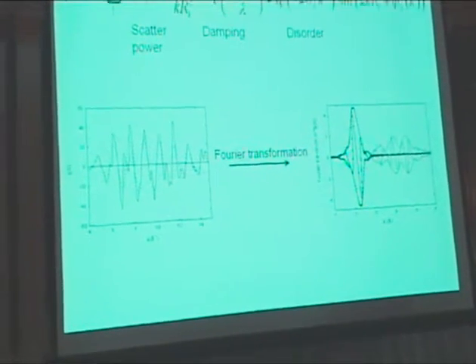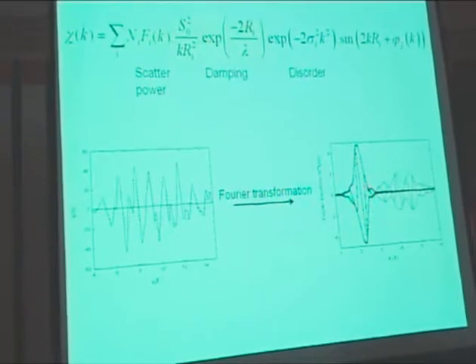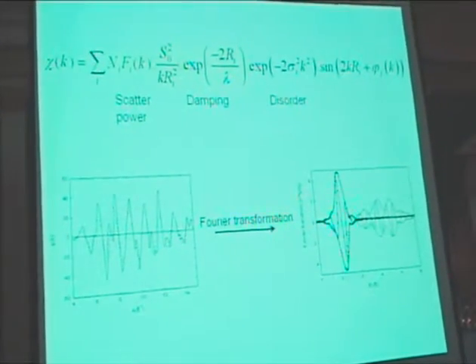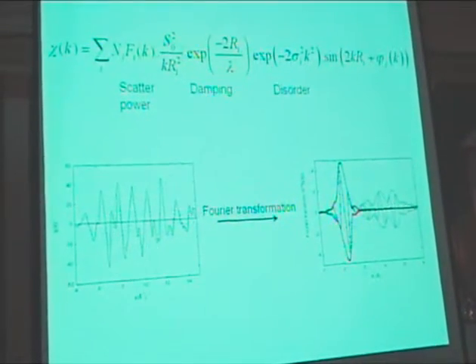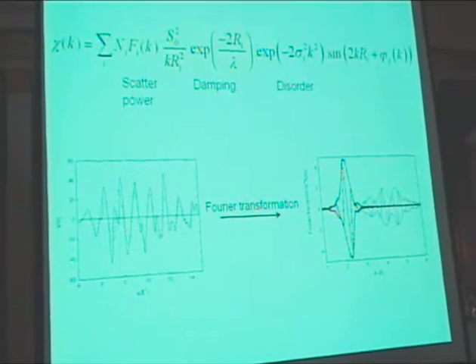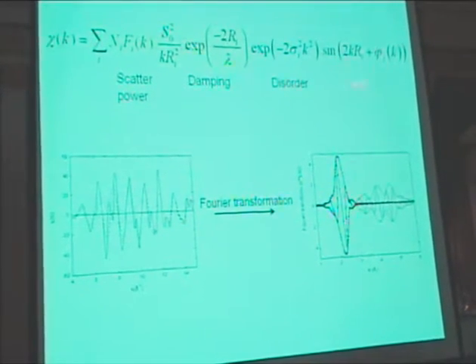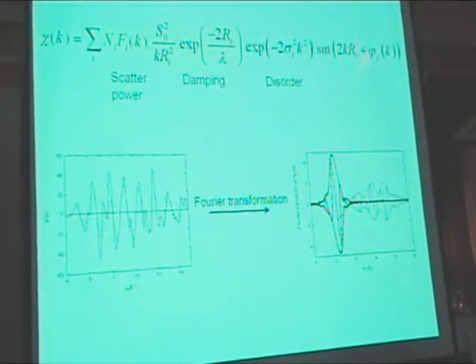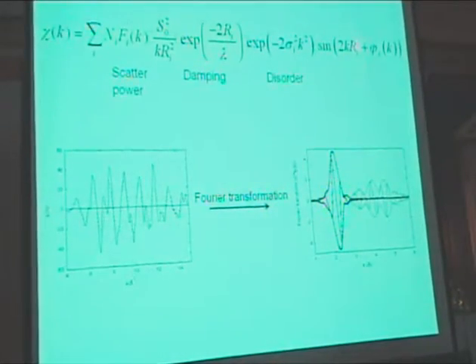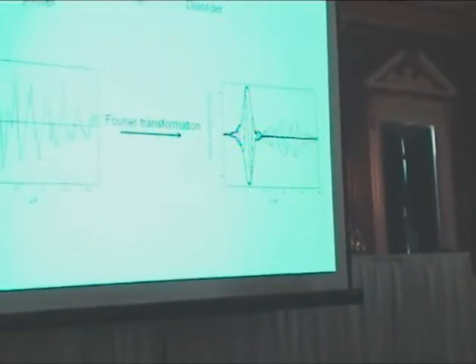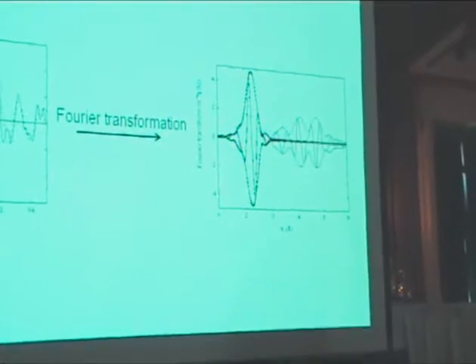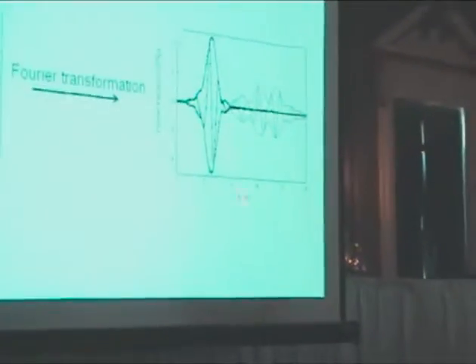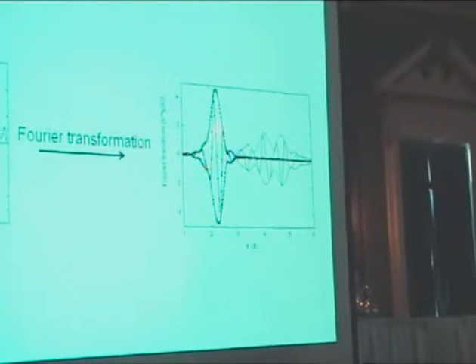And then Professor Stern from Seattle came up with the idea, which in those days was very new, but nowadays everybody is doing this anywhere in spectroscopy. Just do a Fourier transformation. When you have a formula like that, you just Fourier transform and you get peaks wherever there is a certain R. So if I Fourier transform this and I go from K space, which is energy space, to R space, distance space, I get peaks roughly at the position where my neighboring shells are.